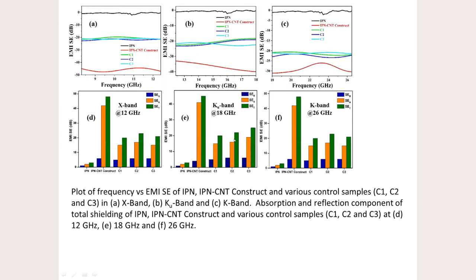So now we have carried out the EMI shielding on these membranes. EMI shielding is measured in dB. Higher the dB, higher the shielding, in terms of practical applications. So all our membranes, which have carbon nanotubes sitting over them, do show very high shielding, greater than 40 dB, in a very broad band frequency range. As you can see, from 8 gigahertz all the way up to 26 gigahertz, we have very high shielding.